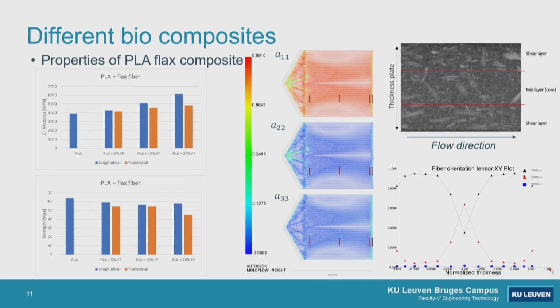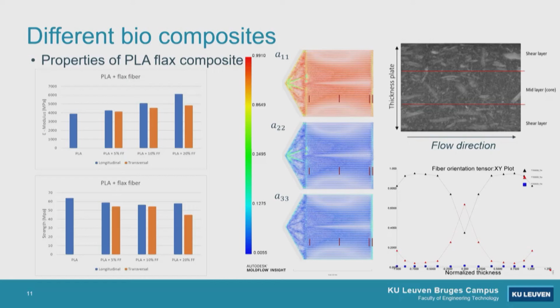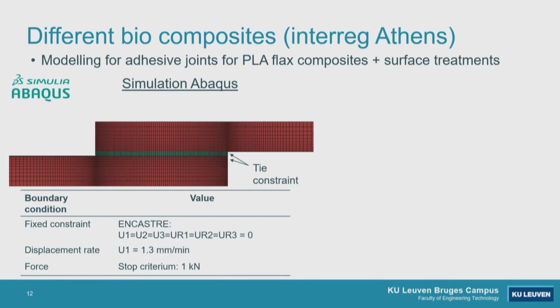So we of course also control the orientation of the fibers in the plates at different locations. This can be done using X-ray micro-CT and can be compared with this numerical simulation result. If you also have a look into the top right picture, it's not only fibers, but also some shives are still present in the type of material which is used in this type of applications. So that's the PLA flax composites. Later on I will compare all of them. So that's the first one in the competition.